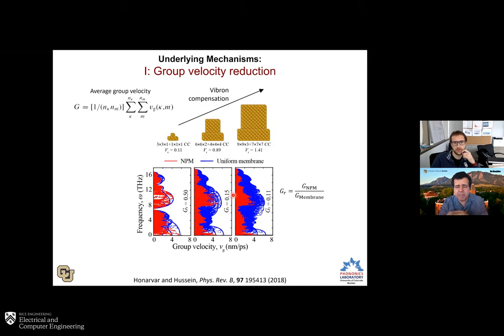So now if we take this aspect and explore it a little deeper, we can, for example, formally quantify what happens to the group velocities. So this is the entire spectrum up to around 17 terahertz. And what this figure shows is an average quantity that represents the ratio of the NPM group velocity to that of a pure membrane. So we want that quantity to be as low as possible. And in fact, we can see indeed that as we engage in this vibron compensation methodology or approach, we reduce the average group velocity. So that's favorable, and that suggests that we are going to get stronger reductions in the thermal conductivity.